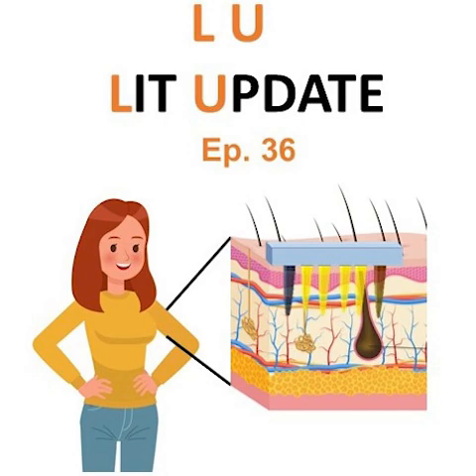Very long time. Yeah. Now, the human body is a very complicated system, and there are other factors that you must consider when you're making wearable sensors. And one of them is what happens when your interstitial fluid's pH changes. And it can happen if you have certain diseases. Now, does the sensor's response change with different pH levels at all? No, it actually doesn't. There were no significant changes observed with changing pH levels, which is great. Yeah, that is really great. And now, how about other potential biomarkers that might interfere with the sensor response? Well, in the presence of other ions such as potassium and calcium, the sensor response didn't change significantly.